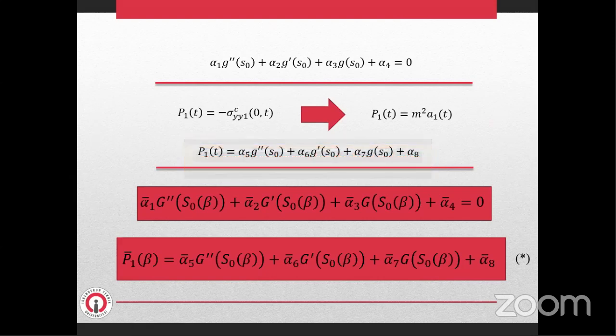The dimensionless forms of these equations are shown below. For obtaining the contact pressure, first we solve the first equation to calculate the residual stress function, and then substitute into the second equation to find pressure. For calculating the residual stress function by solving the second-order ordinary differential equation with variable coefficients, we use state space representation since the residual stress function is very stiff.